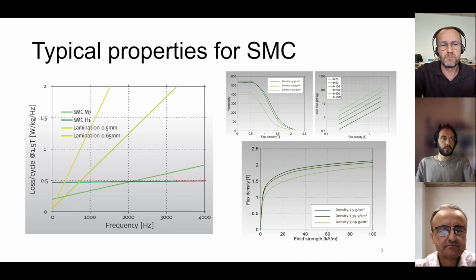Typical properties of SMC, if we look down here, the saturation level, we can typically reach the same saturation levels as you can with iron. So around 2 Tesla is reachable. Then when we go into motors or frequency applications, we see some loss curves as a function of frequency.